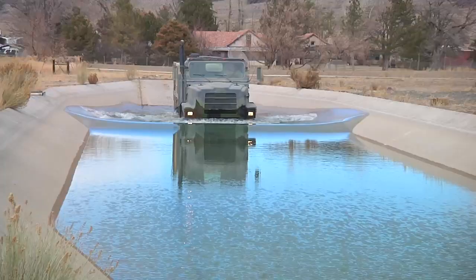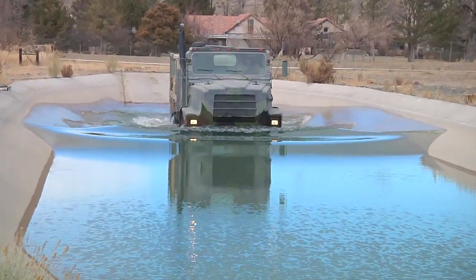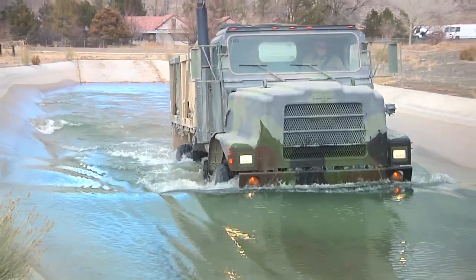Okay, now, here's the fun part. These guys actually drive these vehicles through a shallow saltwater pit and then through a slurry of dirt, grit, and saltwater, which causes both corrosion and wear inside the joints and crevices, accelerating the degradation of these areas. These corrosive solutions are representative of the typical environments that these vehicles are exposed to on a regular basis.